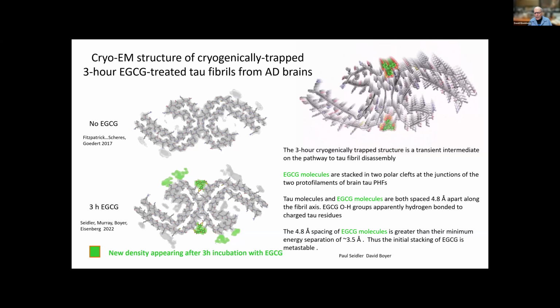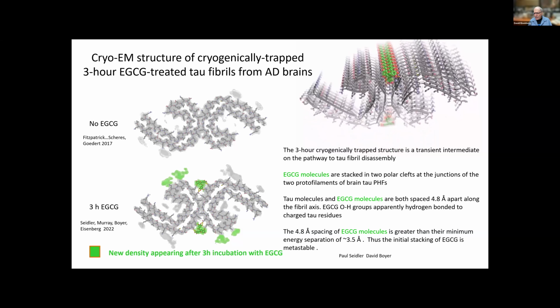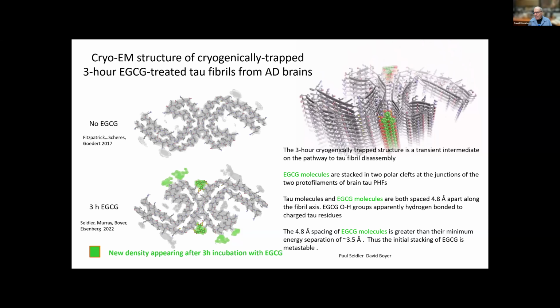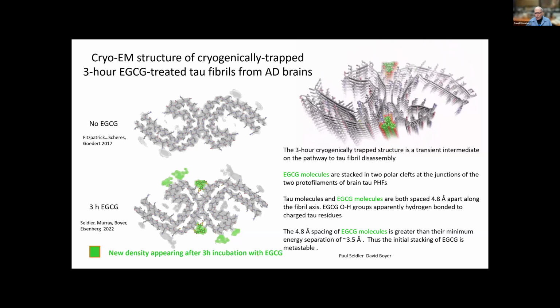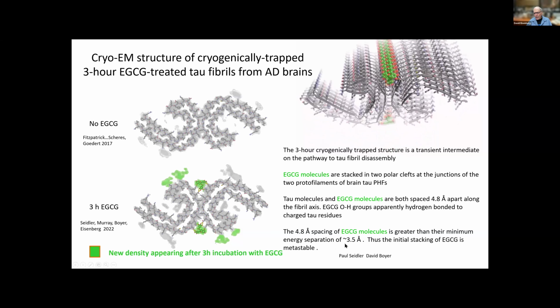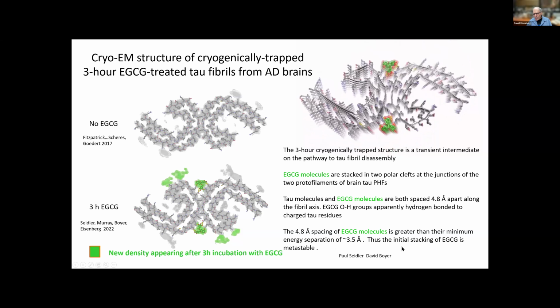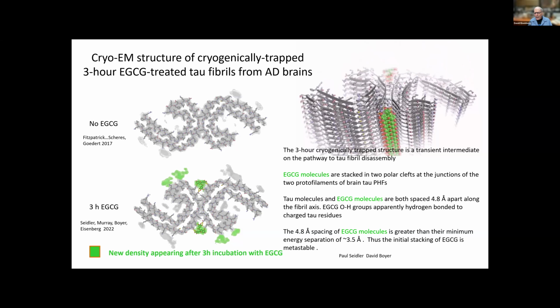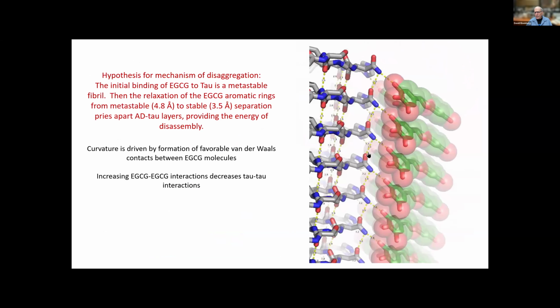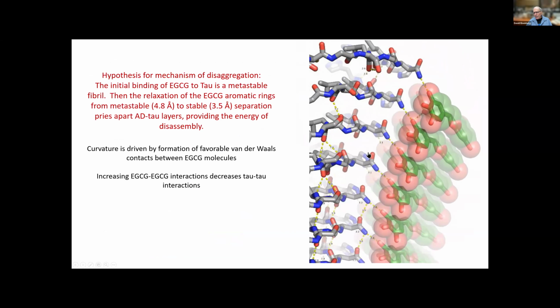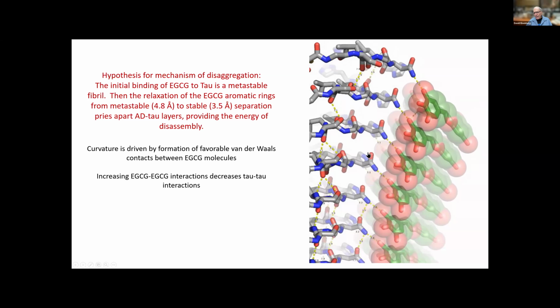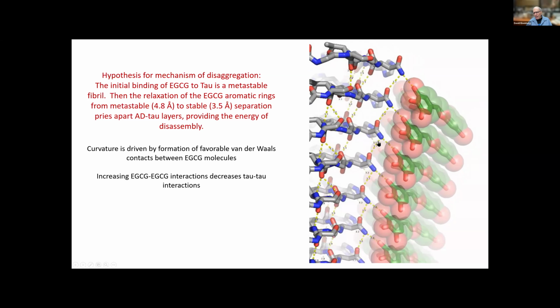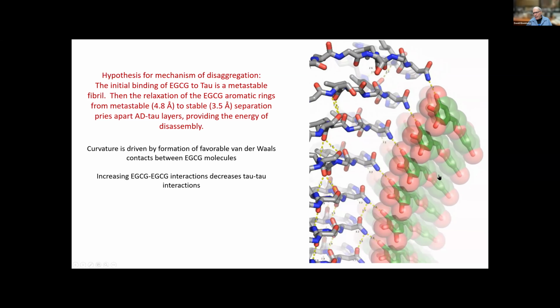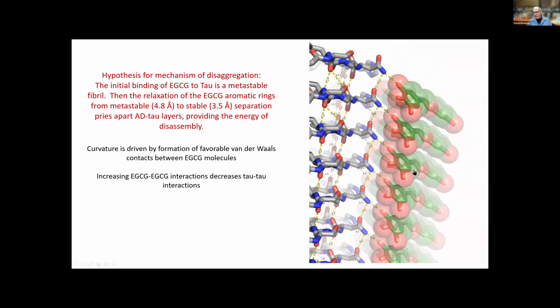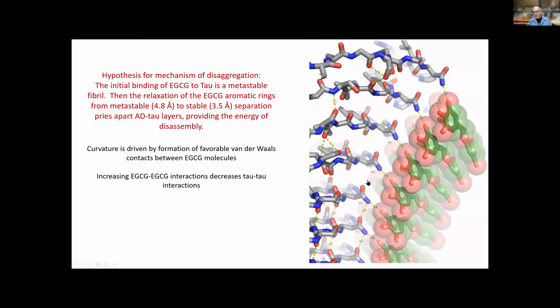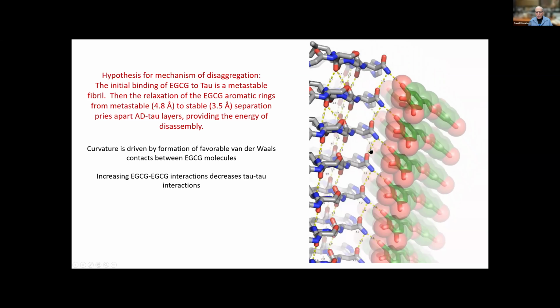But that 4.8 angstrom spacing is greater than the minimum energy separation of the rings of EGCG, which, as Pauling taught us, is more like 3.5 angstroms. Thus, the initial stacking is metastable. And our hypothesis is, based partly on molecular dynamics, that the EGCG initially bound, so the rings are 4.8 angstroms apart, undergoes a transition, and that transition exerts a torque on the fiber, which helps break it.